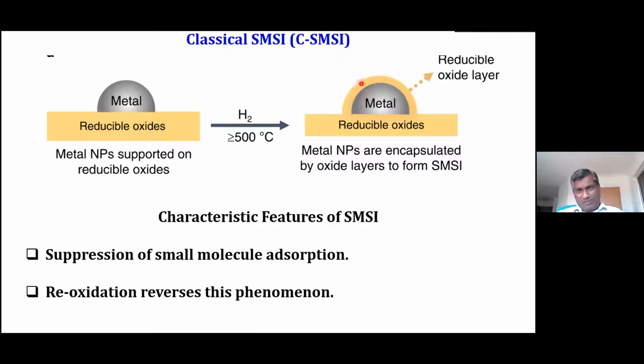So this is called classical strong metal support interaction. The characteristic feature of this SMSI is suppression of small molecule adsorption. For example, because the metallic sites are completely covered by a layer of this metal oxide, these metallic sites are not accessible for small molecules to adsorb, for example, hydrogen chemisorption or CO chemisorption. You can see a substantial reduction in the CO chemisorption level when these metal particles are covered by the metal oxides. I will show you an example in the next slide.